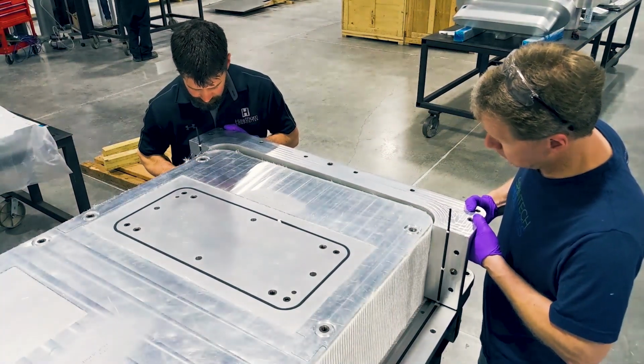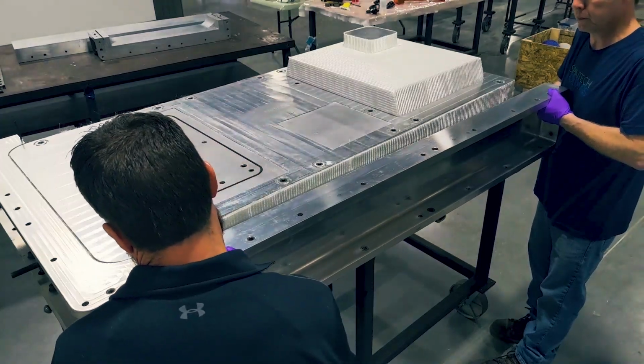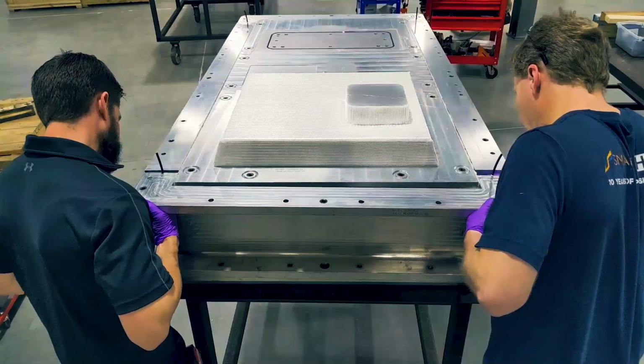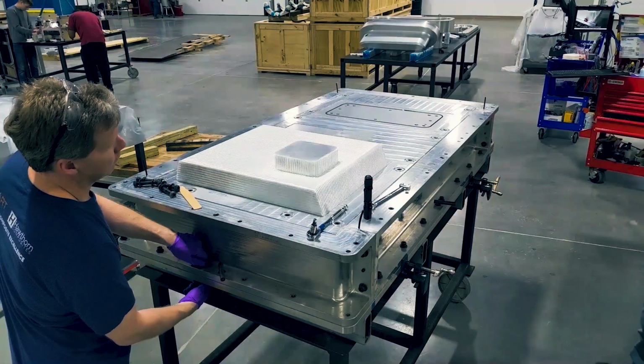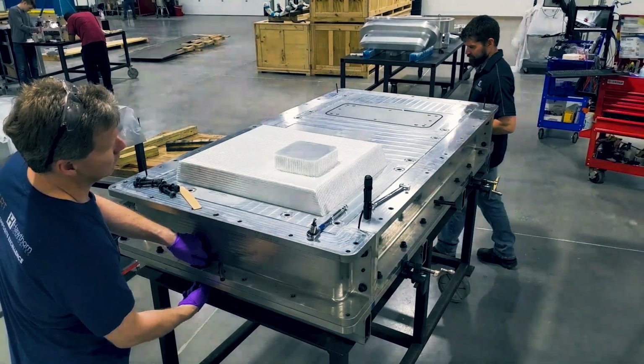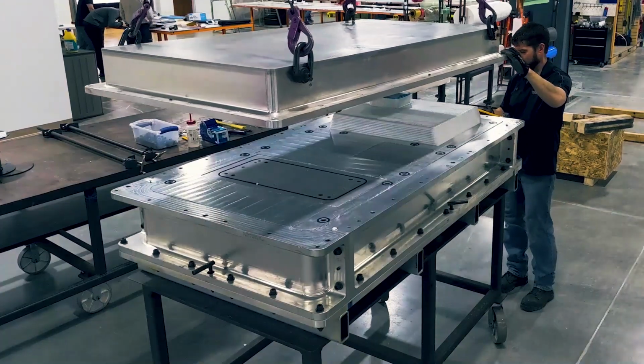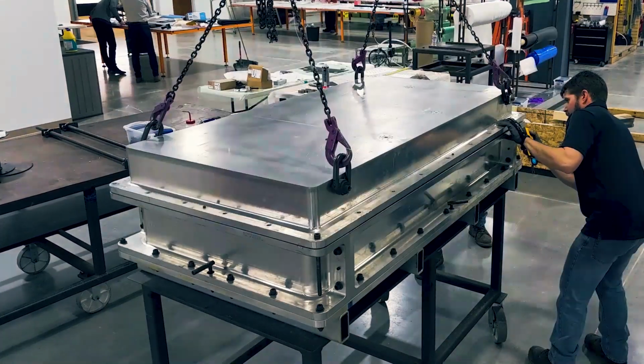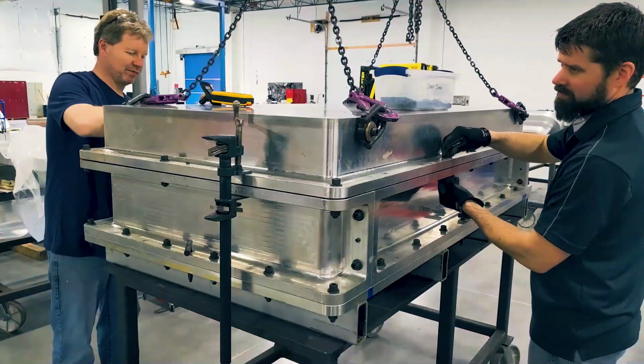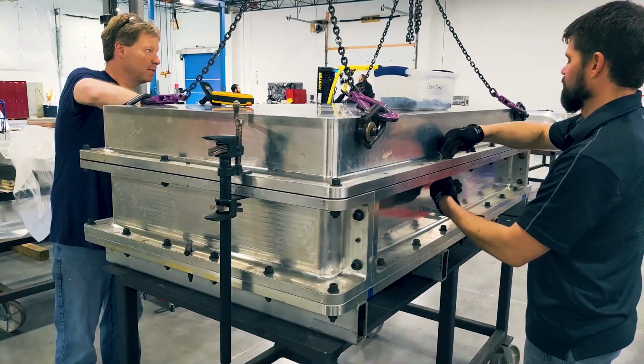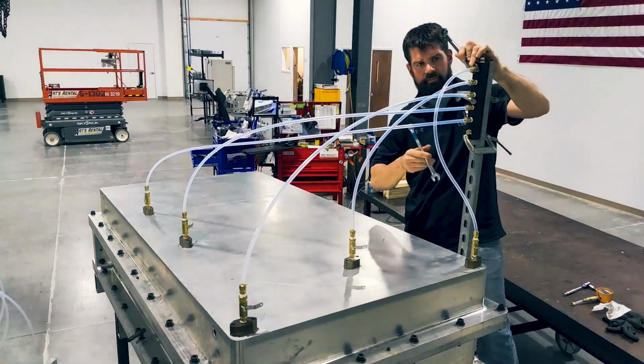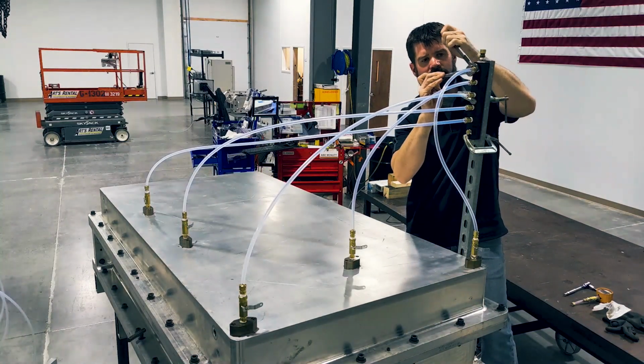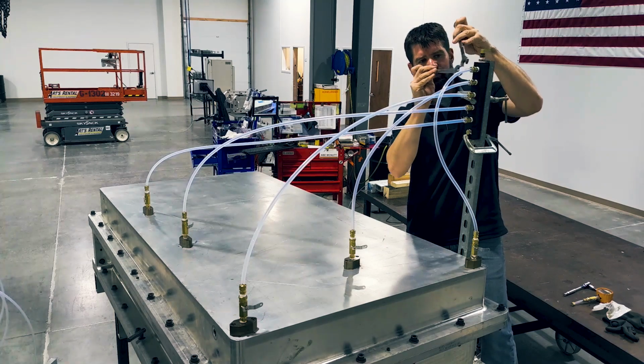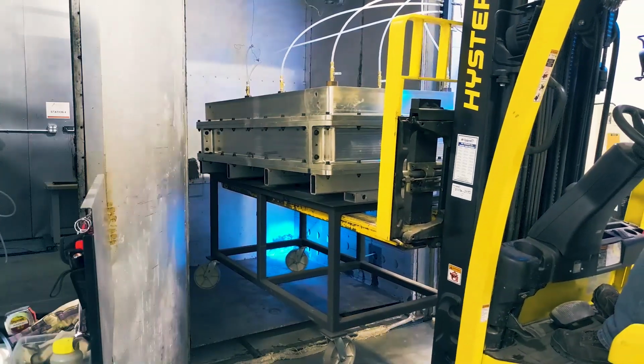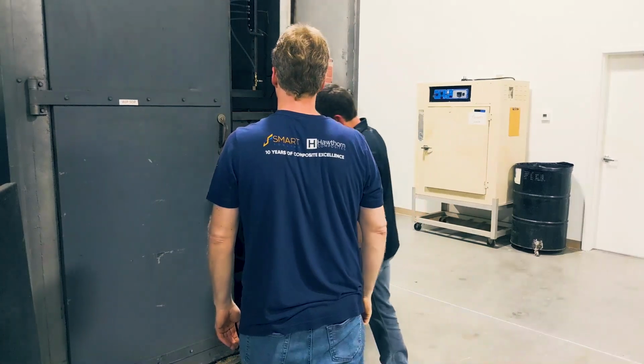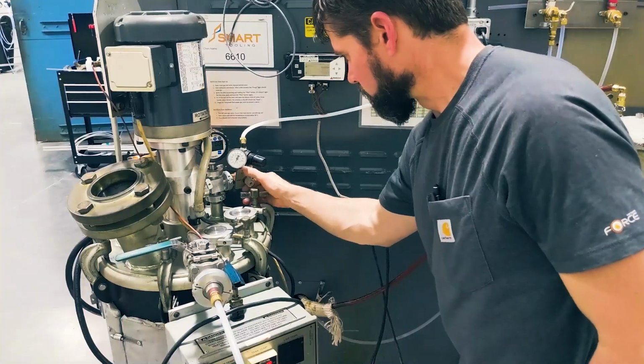After layup is complete, the mold is closed in multiple steps, again because of the requirement for minimal draft angles. The mold is then bolted closed and is plumbed for infusion. The mold has multiple outlets to allow us to control the resin flow of the outlets and make sure no region of the part lacks proper resin infusion. The mold is placed into the oven, infused with resin, and the cure cycle begins.